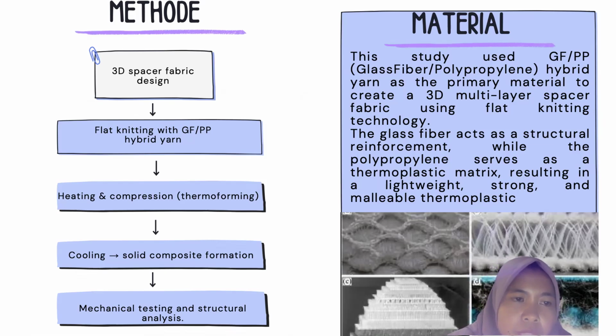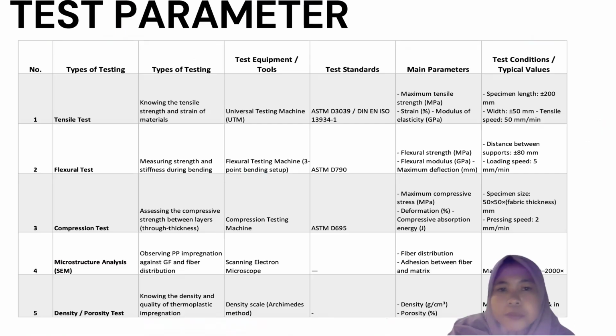3D spacer fabric design, flat knitting with glass fiber polypropylene, heating and compression or thermoforming, cooling, solid composite formation, and mechanical testing and structural analysis. And these are the test parameters used in the journal. One, tensile test: testing the tensile strength and stiffness of the material. Tools: universal testing machine, test standard ASTM D3039.